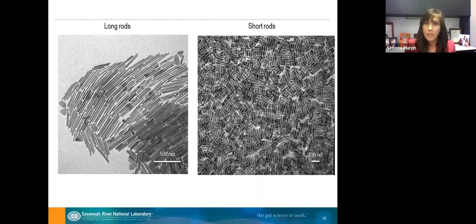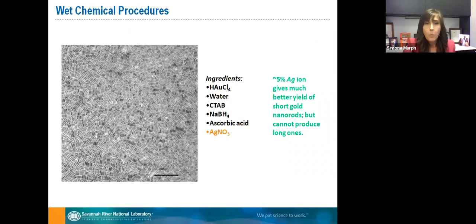And of course, we are all scientists and we know that I'm going to show you the most beautiful SEM or TEM images with the best results. But we had to go through a lot of trials and tribulations to identify the best steps to separate and get a monodispersed system. And what we found in the wet chemical procedure is that about 5% additive ions, in our case silver ions, allow us to get a great yield of these nanorods. So we call these the short rods.